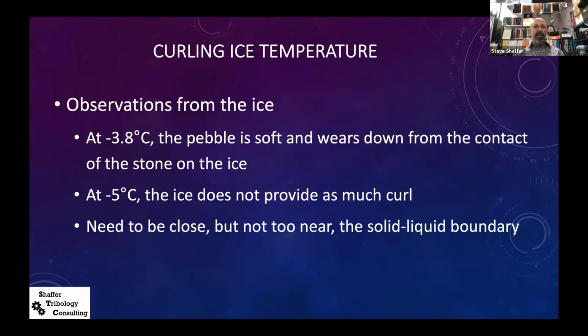So what we observe is if we warm the ice from that -4.5, if it gets up to about -3.8 or higher, the pebble is soft and it really wears down from the contact of the stone on the ice, it just wears down too quickly. If we go lower, not much lower, at -5 degrees, we don't see as much curl. So we need to be pretty close to, but not too near, the solid liquid boundary.